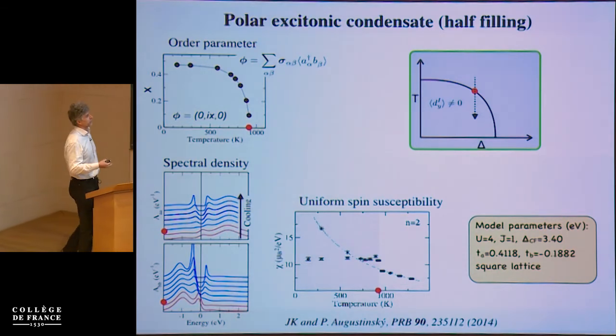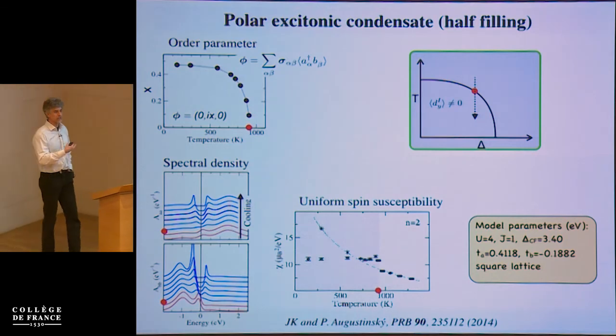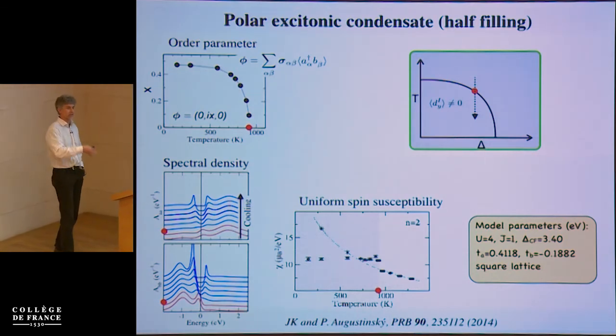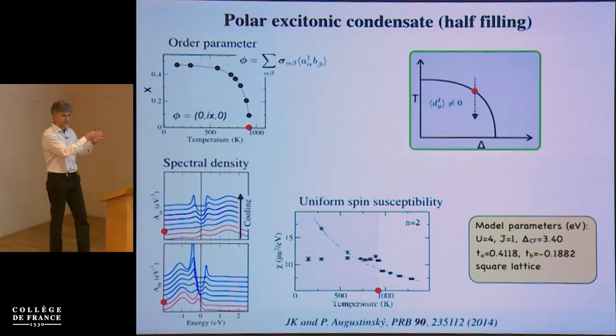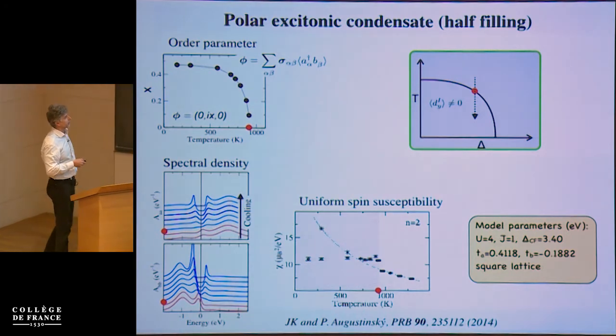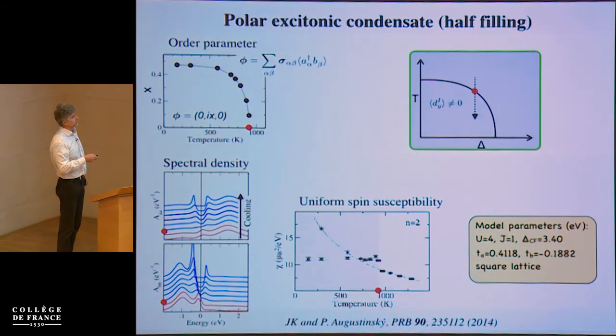The other thing we can look at is the spectral density. This is fermionic spectral density, something that does not exist on the level of the bosonic model, of course. What you see here is the spectral density of the A and B electrons in the normal state. These different curves correspond to different temperatures. Here's the high temperature region, and this is decreasing temperature. And you can see in the normal phase we have essentially 2 touching bands, an A-like band and a B-like band.